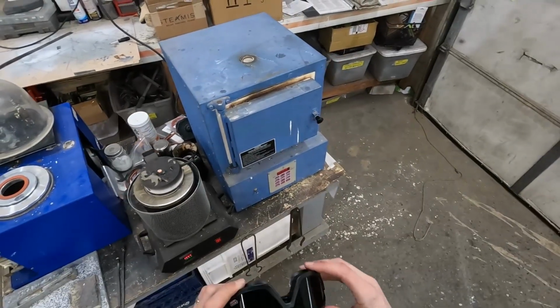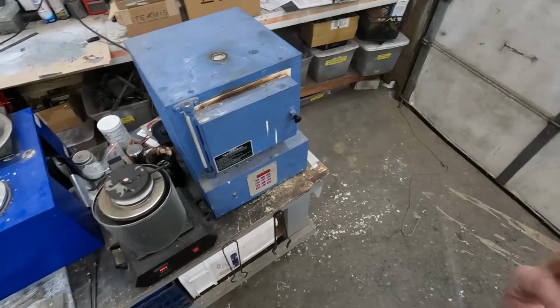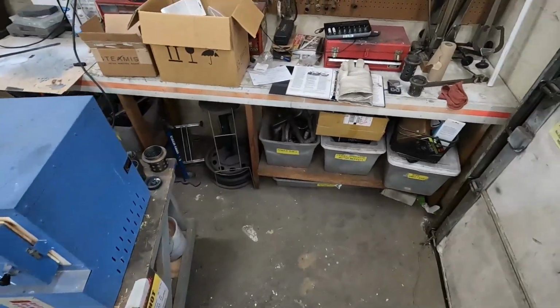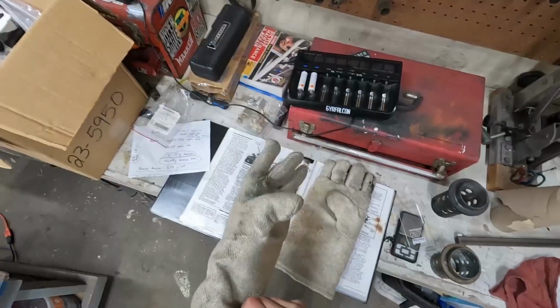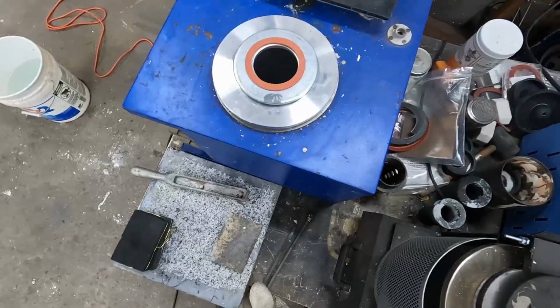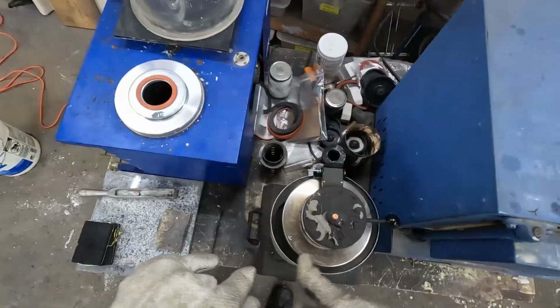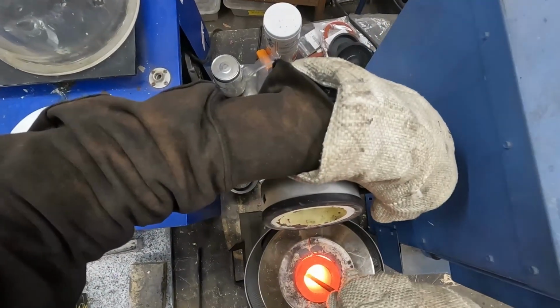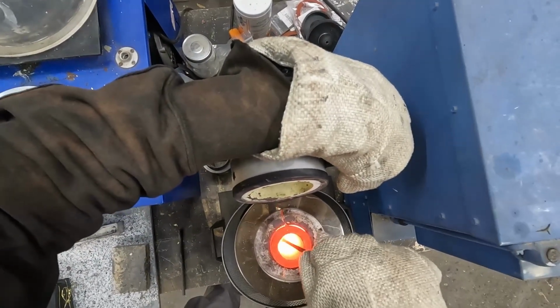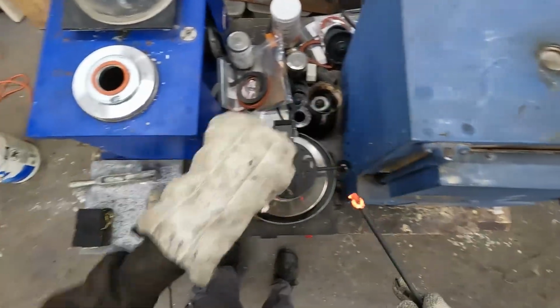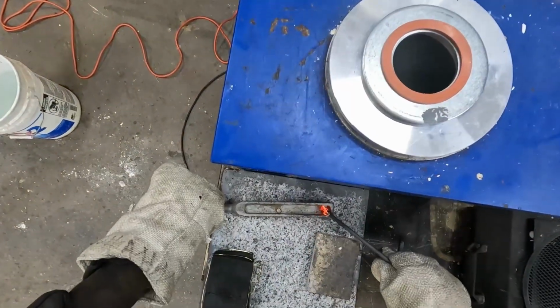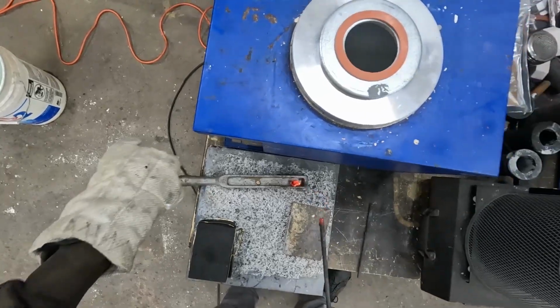It's important for this part when you're looking at molten metal to use dark goggles because there's infrared energy coming off that could potentially damage your corneas. Putting on these gloves here, we've got these carbon stirring rods that you can use to poke the metal and stir it. When we look inside, you can see how fully liquid it is, and the carbon rod will attract any impurities that stick to it, and they pop off like that.